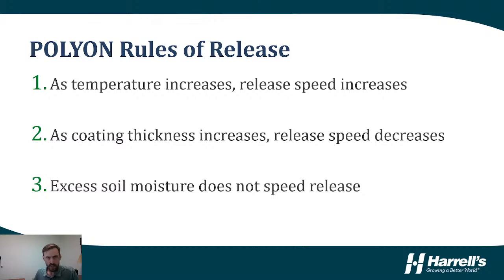I want to reiterate that as coating thickness increases, release speed decreases, and that is something that we control during the manufacturing process. So if we want a material to use in the heat of summer that's going to release a bit slower, then we can create a material with a thicker coating so that release is going to fit the expectations, regardless of what those expectations may be for your specific agronomic program. So this isn't just one product. This is a family of products that can be tailored to suit your specific agronomic needs.